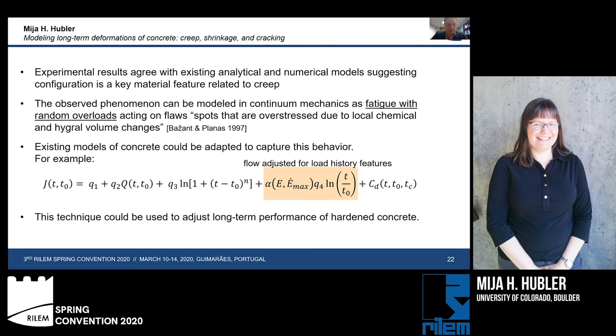For example, we could adjust a flow term in our rheological expression to include load history features that we might anticipate. For example, for a bridge, if we anticipate a certain frequency of loading, a certain frequency of overloads, this could be incorporated into our creep equation. The technique could also be used as a means to adjust the long-term performance of previously hardened concrete.